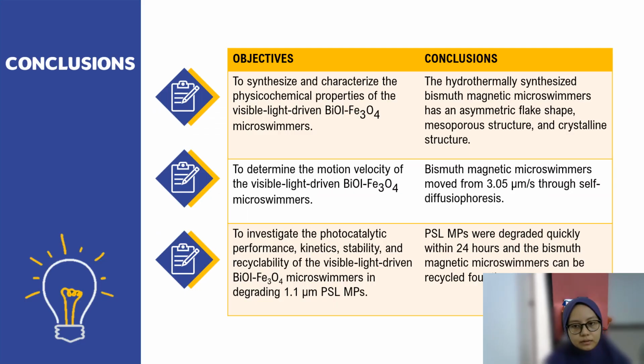It can be concluded that the mesoporous structure, crystalline structure, and asymmetric flake shapes of bismuth magnetic microswimmers were synthesized, and they can move at 3.05 microns per second through self-diffusiophoresis. It also can degrade the microplastics quickly in 24 hours, and the microswimmers can be recycled 4 times.